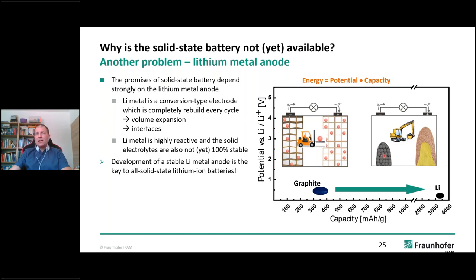When we use lithium metal anodes, this is different, because we are actually rebuilding the anode every time we cycle the cell. When we are discharging, we take away all the lithium, put it in the cathode, and ideally nothing remains on the anode side. And when we are recharging, we have to completely rebuild it in a rigid system, without flowing electrolyte, on the current collector of the anode, which is actually very, very difficult. This is the problem: we are changing the volume of the cell and always making new interfaces. As I told you, the interface is a big problem.